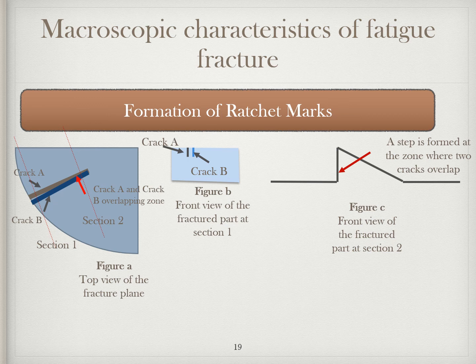Figure B shows that the two cracks are in the same plane. These two cracks overlap after propagating a certain distance. So here we see crack A and crack B in the same plane. This is the front view of the fractured part taken at section 1. This is section 1 over here.